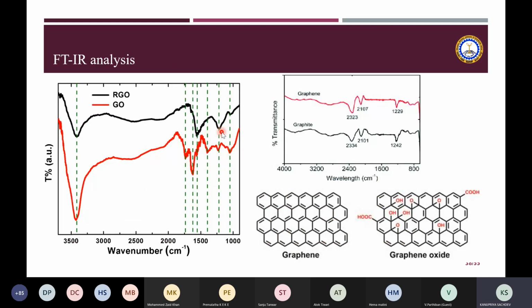The FTIR again gives you the presence of the functional groups, and you can see that as we go from GO to RGO, the functional groups are removed. Here, this shows you the graphene oxide with the different functional groups. Not all of them are removed, but depending on the efficiency of your reducing agent, most of them will be removed, and that is why the intensity of the peaks decreases as we go from GO to RGO.